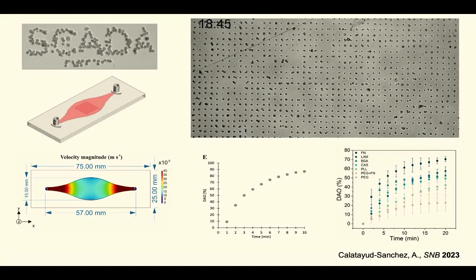The interesting thing of this is that the curve will have a different type of shape or a different final array occupancy depending on the affinity of the cells for the substrate. So what you are seeing in this graph is what happened when I modify my pattern, and instead of having fibronectin, which the cells have a high affinity for, for example, I put PEG or BSA. I can see how the cells cannot fill the whole array, they do not have the affinity to do so, and I can easily quantify that in a 20 minutes time. So this device is useful for at least determining different affinities of cells for matrices.